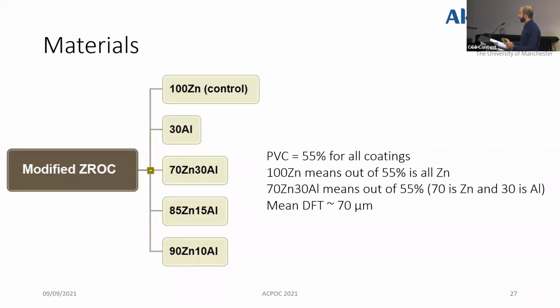So AkzoNobel provided us with these 5 formulations: the 100 zinc, which is the control one, then 30 aluminum, 70 zinc, 30 aluminum, 85 zinc, 15 aluminum, and 90 zinc, 10 aluminum coatings. The PVC of all these coatings is 55, so 100 zinc means that out of 55 it is all zinc. For 70 zinc, 30 aluminum, it means that out of 55 volume percent, 70 is zinc and 30 is aluminum. The mean dry film thickness of all these coatings is about 70 micrometers.